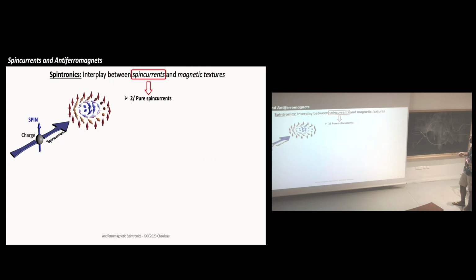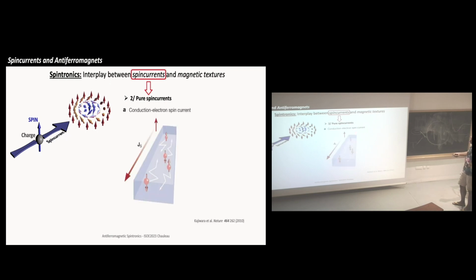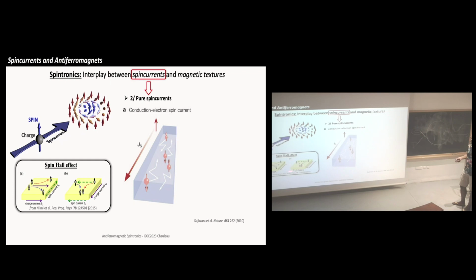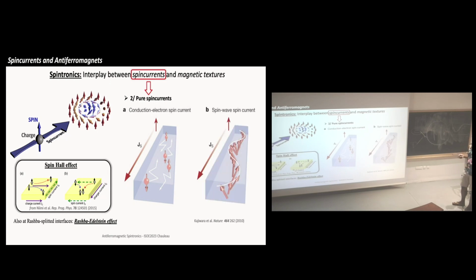But now there are some more fancy spin currents, and the first one is pure spin currents. In pure spin currents, there are some materials where the spin up and spin down like to travel in opposite directions. This usually happens in materials showing strong spin-orbit coupling, where there is a spin Hall effect. I will talk about that a bit later, but Michel already introduced it. And there is a third kind, which is also a pure spin current, and this will be important for us. It can be conveyed by spin waves. Because a spin wave is a magnon, and a magnon can carry ħ, so it can carry angular momentum. So the pure spin current can be carried by spin waves. And here it is also very interesting, because you don't have any Joule heating, since you don't have electrons, they are insulators, so that could be quite interesting. So this is the concept of spin current.